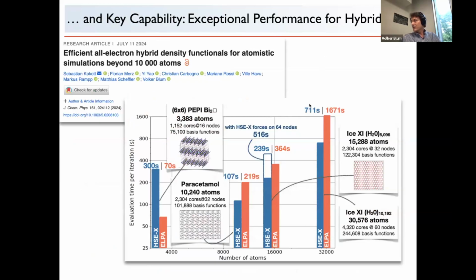Second, we have the hybrid functionals, and I mentioned that in the beginning already. This paper appeared very recently. This really is hard work by at least 10 people, actually more, for 15 years, I would say. This paper in particular is work by the lead authors over 5 years, trying to use practical programming paradigms like the MPI-3 standard, which allows you to do shared memory, but controlled inside the code. So the user doesn't have to worry about this control. The code will do this for you. That works quite well. Better load balancing, better limiting of memory for large systems, blocking to optimize on CPU architectures and so on.